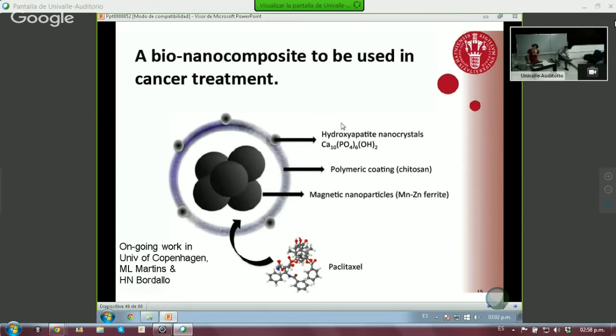As you can see here, the magnetic nanoparticles are manganese and zinc ferrite, shown here. What they do is similar to what we're doing. They have a polymeric coating around it, and the drug in this case is paclitaxel, which is also incorporated inside. And they use some nanocrystals made of hydroxyapatite. With this, they are targeting the cancer cells.